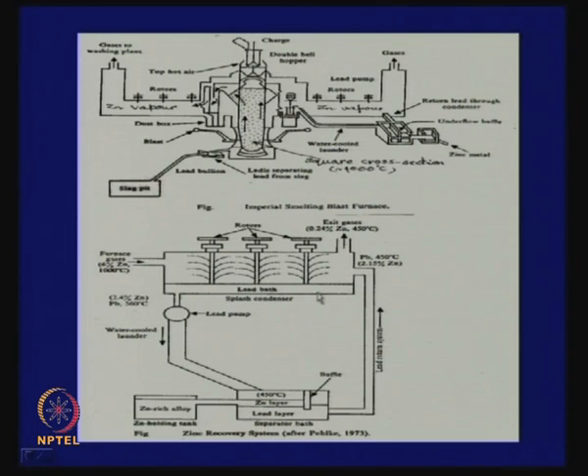Now, this lead bath would contain 2 to 4% zinc according to the phase diagram there on the right hand side. Then it is cooled and it gets separated out, cooled only slightly. The gas is coming at 1000 degrees, and the lead bath is at about 500 degrees.